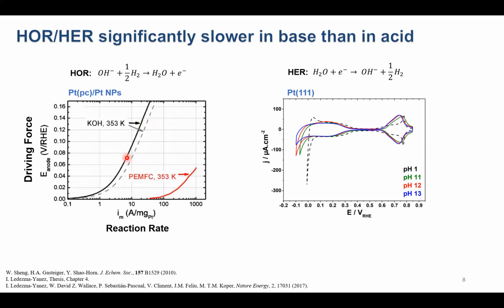We'd really like to understand why electrolyte pH has this big effect. We think we can make less expensive alkaline fuel cells than our very expensive acid fuel cells, but to do that, we need to keep the high activity that we see in acids. So we really want to understand, how does pH cause this effect? I'll just briefly mention, we see a similar effect on hydrogen evolution, and in particular, we see this even at very high pH. And so here, again, we're showing the reaction rates, and you can see at any given potential, the rate is lowest at pH 13 than it is at pH 12 or pH 11. And so we really want to understand, what is the effect of pH?